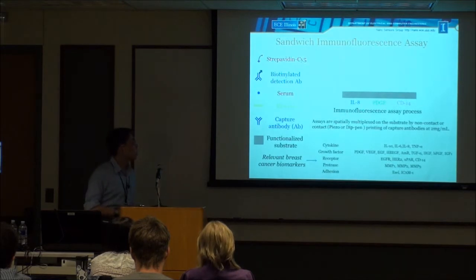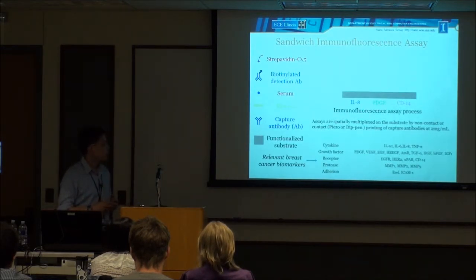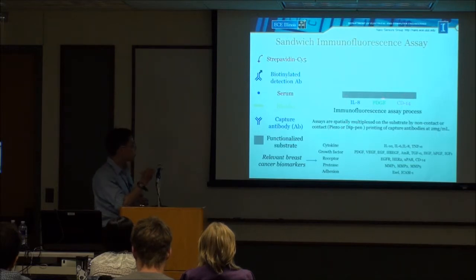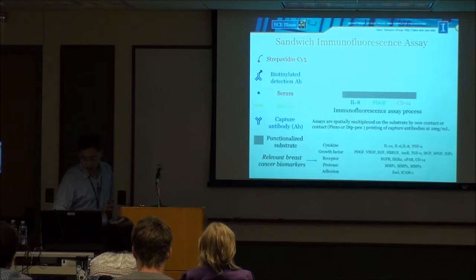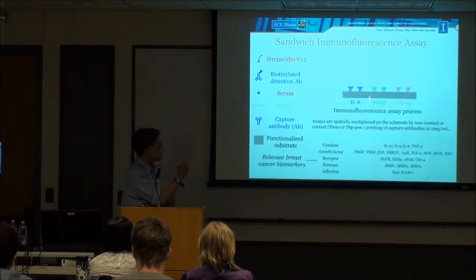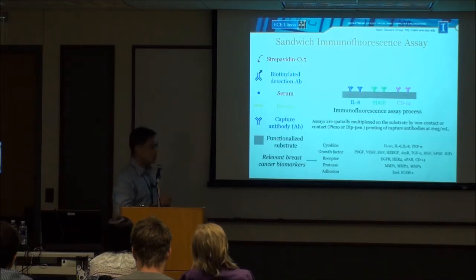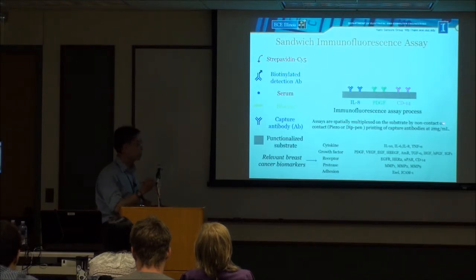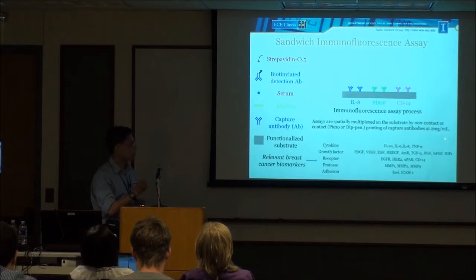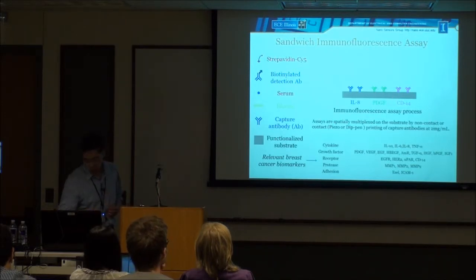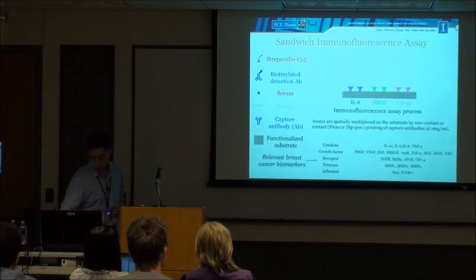Let me show you how we made those cancer biomarker microarrays and how this immunofluorescence assay works. On top of the photonic crystal substrate, which is functionalized with a certain type of silane, we first spot different types of antibody. Our collaborator gave us 24 different types of antibody, which belong to 5 different families. We use a non-contact printing method to print a pretty high concentration of antibody, at 2 milligram per mL. We first print the different antibodies on the substrate, and then block the substrate using a blocker to prevent other molecules from attaching to the surface.